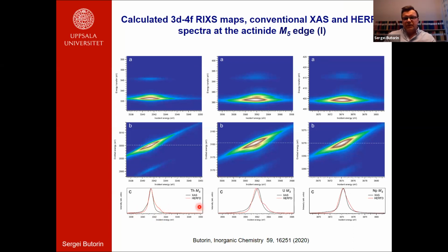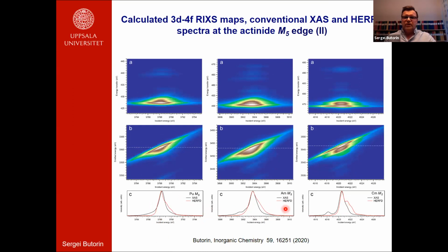So there are systematic differences, as you can see, between HERFD spectra and X-ray absorption spectra at these M5 edges of actinides. One of them is the lack of intensity on the low energy side of the HERFD spectra, which are in red. And another one is the appearance of additional transitions on the high energy side of the HERFD spectrum. Here, it's even more pronounced for plutonium, americium, and curium. So you can see here.